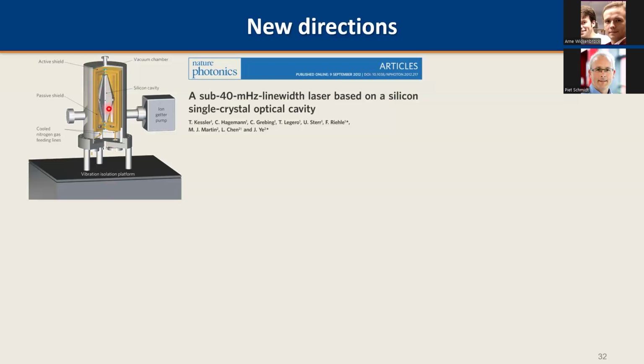Now you still have the thermal expansion problem. Silicon has a zero crossing in the thermal expansion coefficient at 124 Kelvin, so you have to cool it. This is why you have many shields, and there's essentially nitrogen cooling inside the system.